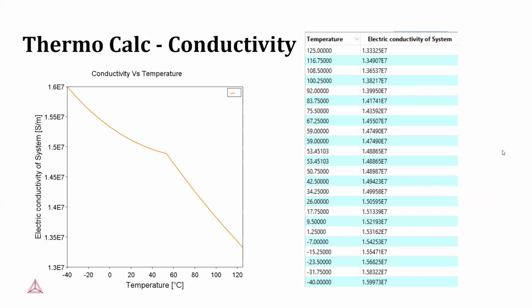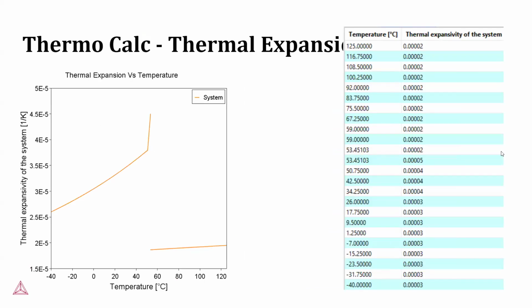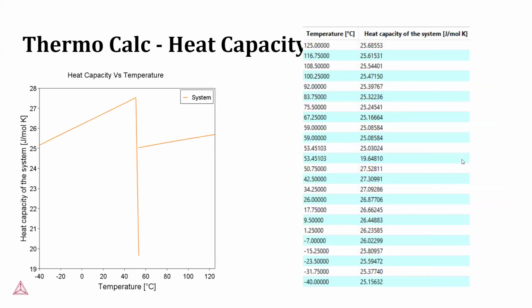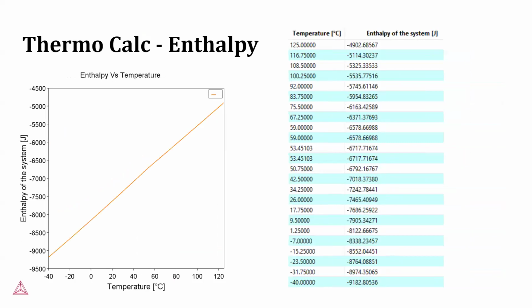So here are the results for conductivity. As temperature increases, the conductivity decreases. For thermal expansion, again, you see that massive jump that wouldn't really be there in reality, but it's what the simulations show. It increases until it hits about 50-ish degrees, and then has a massive drop. For heat capacity, you have the same thing, a massive drop, and then it goes back up again. And then enthalpy is not dependent on the phase as shown here, but does increase with temperature.